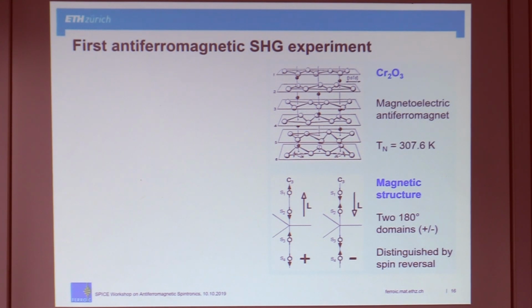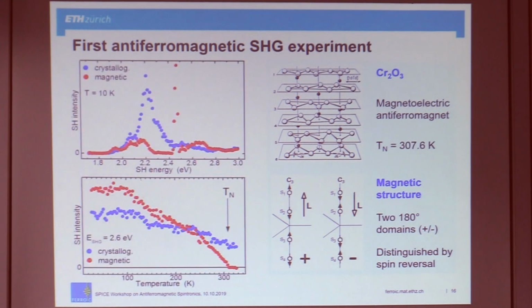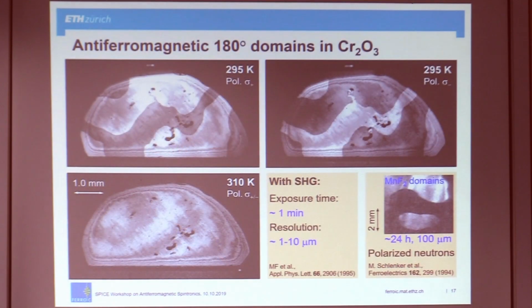So you take the second harmonic spectrum, you find two contributions. One is magnetically induced, antiferromagnetically induced. The other one is crystallographically induced. The crystallographic one changes a little bit with temperature. But the magnetic one goes away abruptly at the ordering temperature. So it's a very clear signature of the antiferromagnetic order. You can now take these two contributions and let them interfere, and then you get pictures of antiferromagnetic domains in this material. Typical picture takes a minute, and you get the optical resolution of 1 micrometer.